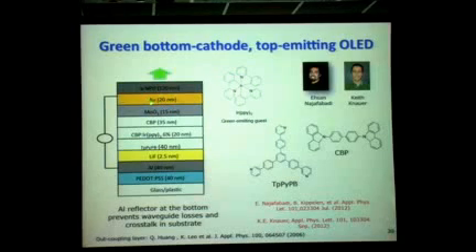You'll notice here that there is no ITO anymore, which is also good because ITO is brittle, so if you want to make highly flexible displays, you're limited if you use ITO, and ITO is also quite expensive. The light is emitted through that very thin top metal layer, a 20 nanometer thick gold layer that has a transmittance of the order of 50%, but you can still get a lot of light out of these devices.